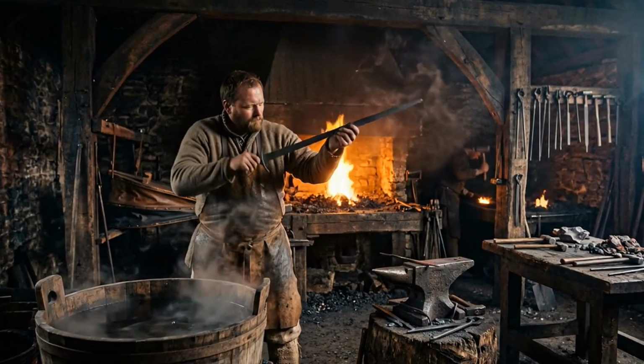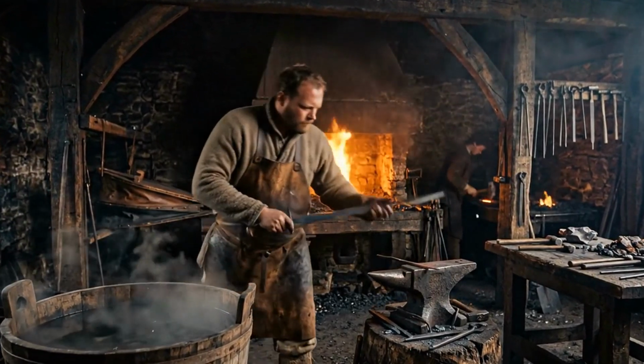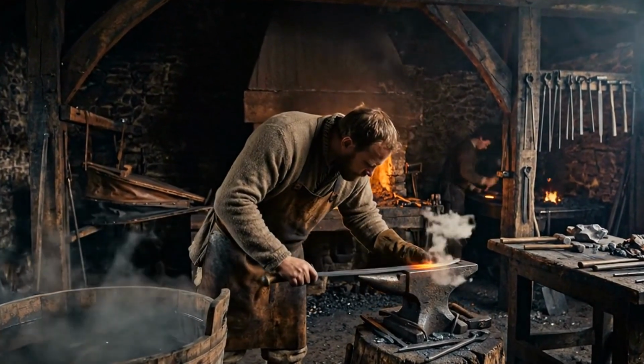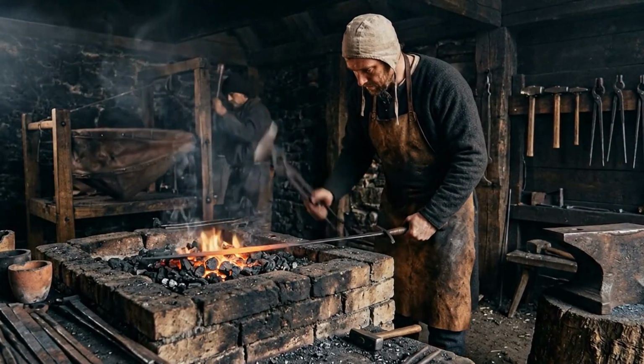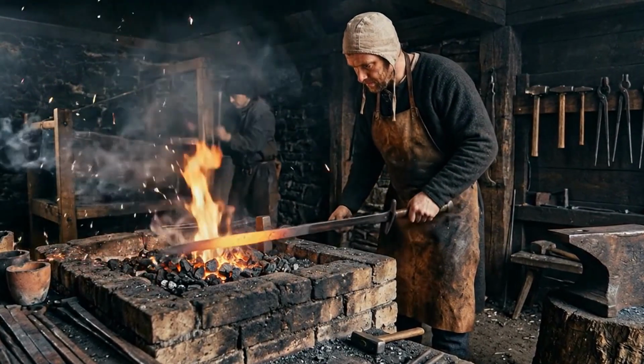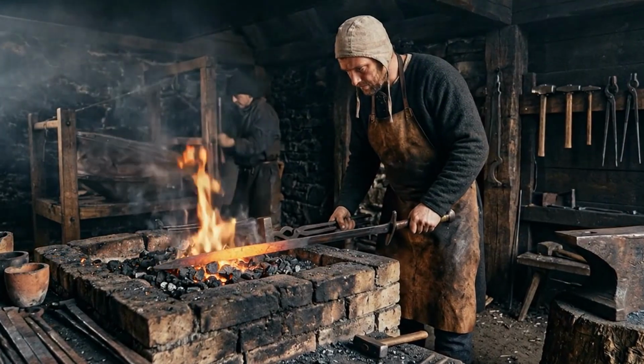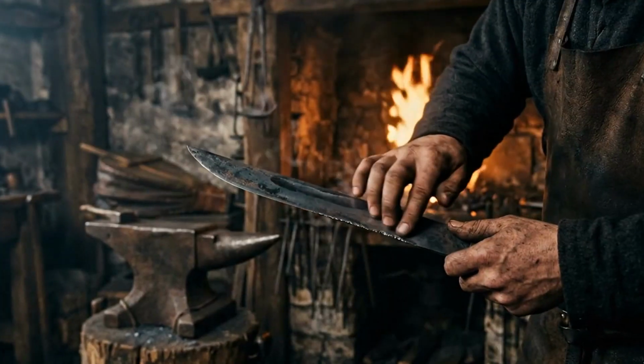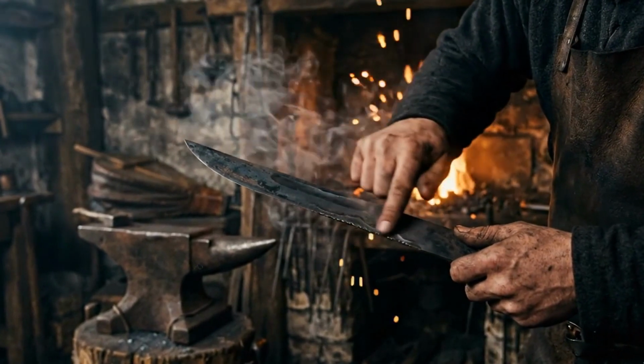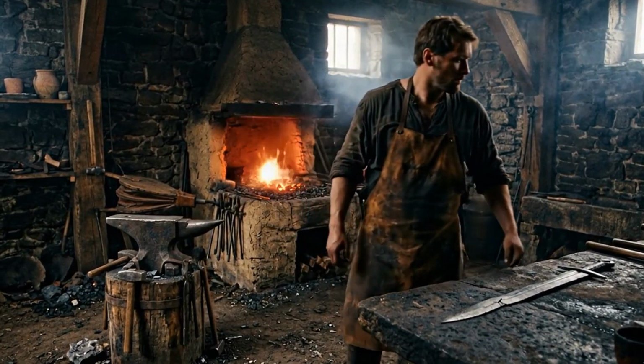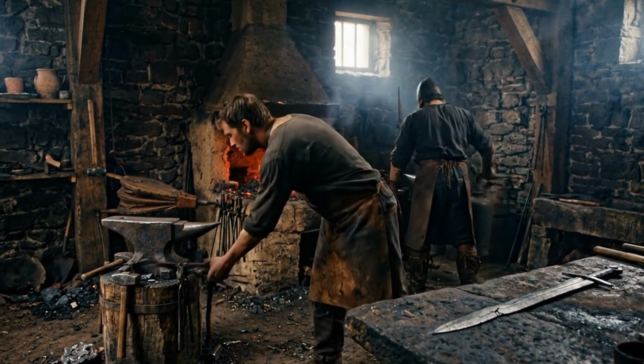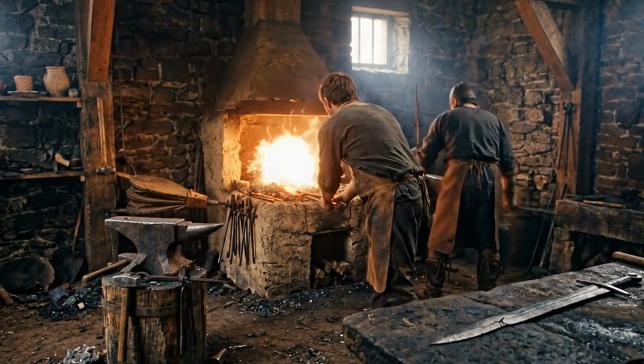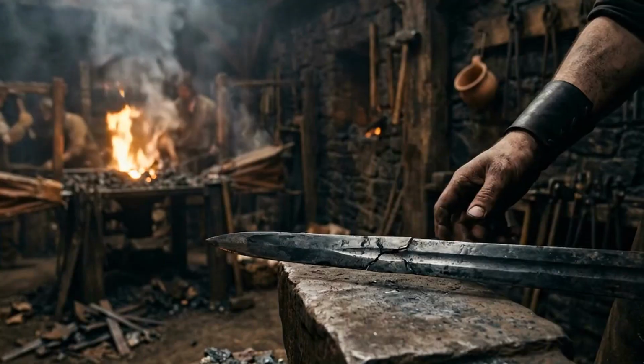After the yakiire, the blade was inspected carefully for warping and cracks. A blade that had warped during quenching could sometimes be straightened by careful reheating of specific zones, but a blade that had cracked was discarded entirely. The failure rate at this stage was significant even for experienced smiths, and the loss of a blade after weeks of work was accepted as part of the process.